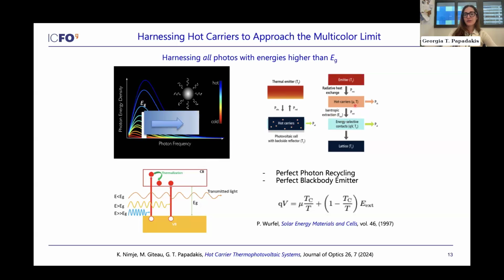So this diagram shows that if I take selective contacts and I can extract hot carriers that are generated inside a PV at temperature T, which is different than the temperature of the lattice, which is T_C here, I get an open circuit voltage that is much higher than the open circuit voltage of a conventional PV. So if I set the temperature T equal to the temperature of the cell, T_C, this term goes to 0, and I recover the standard V_OC of a solar cell.